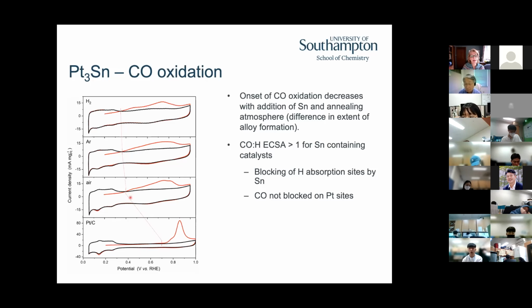And you can see that even if I have tin oxide associated with my platinum particles, I'm seeing that the onset potential has dropped, okay? And it continues to drop as I alloy. So the onset of CO oxidation is decreasing with the addition of the tin, which is well known from the literature, right? So that's good. We're getting the information we'd expect.